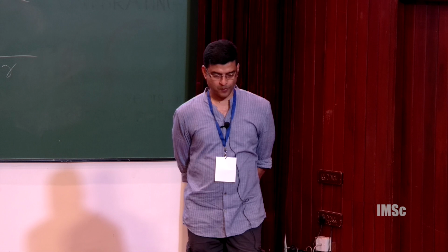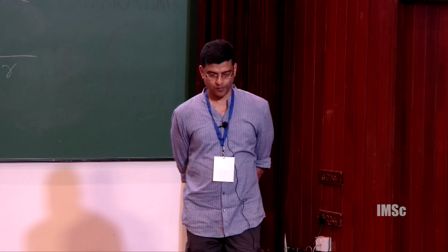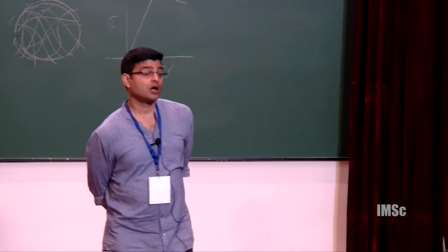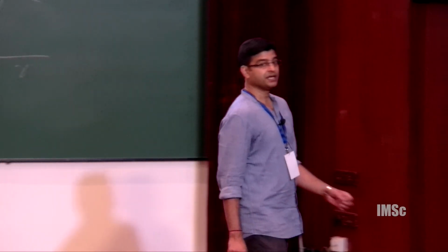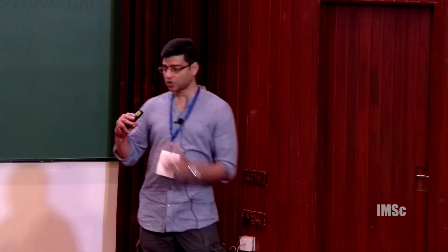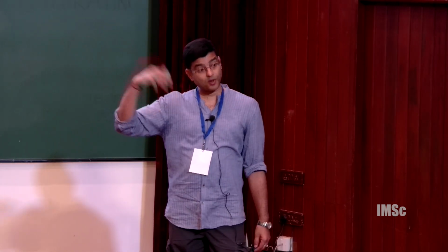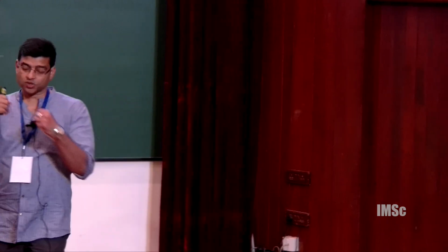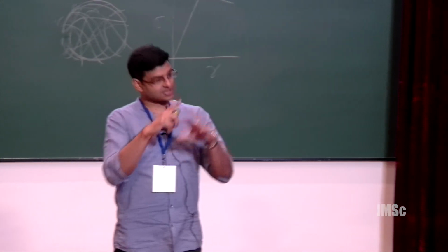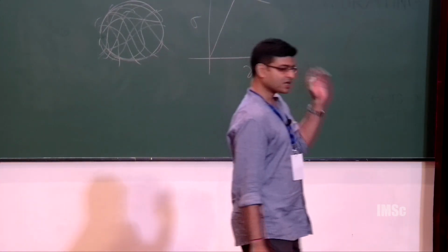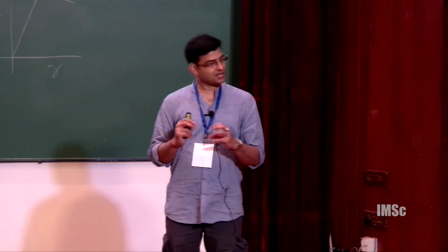You said, is there any aging effect if you make these colloidal particles in aqueous solution and keep them? No, not for these particles, but there are charged colloidal particles that do. To form a gel, they need some salt, and first of all you have to go beyond the volume phase transition, the LCST, where the particles develop some kind of sticky interaction and you can see the strands of the particles. But below LCST, because we are at room temperature, 25 degrees, there is no aging. It's a very, very stable system.